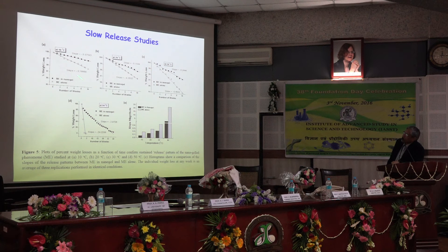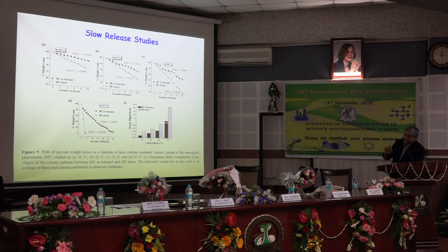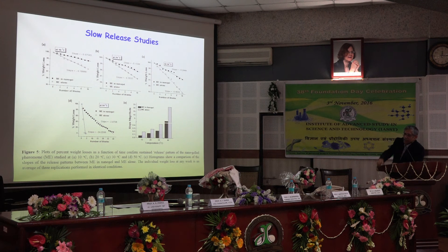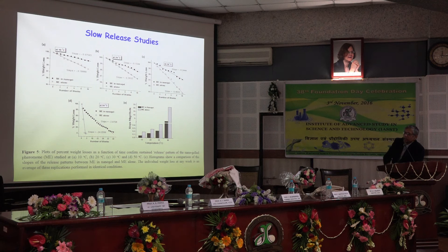You can see the electron micrographs, thermotropic studies, and viscoelastic studies — we have done the physics of them to characterize the material. Most interestingly, we find very different release behavior. Pheromone is normally released in nature based on vapor pressure — how volatile they are. Once we gelate, you can see the slopes are very different: at 10°C, 20°C, 30°C, 50°C. This implies that in peak summer, we can use these gels and the pheromone will be released in a sustained fashion.